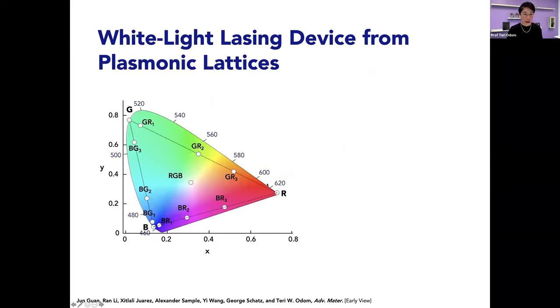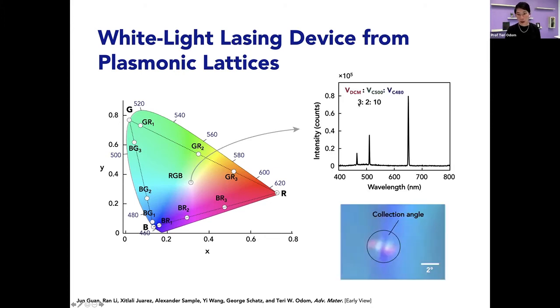And then finally, these are all these data points that we have collected, some that I already showed you. So we're interested in the CIE plot in the center. And so by this empirically determined volume ratio, we're able to achieve these relative intensities. That was the closest that we could do for white light. So if we integrate in this collection angle, this is what we get.